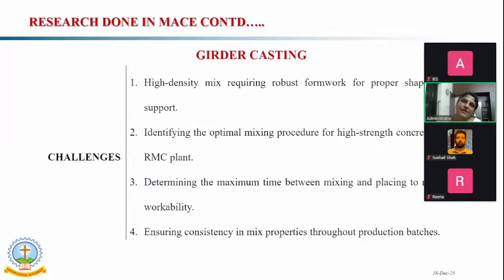The main challenge we faced in the girder casting was the high density mix. As you see in the flow of the fresh UHPC mix, the density was too high. The first time, that was unpredictable for us. When the flow came, the formwork was washed out. That was a very big failure the first time. The second time, we reworked the formwork design and added many bracings, so that we could support the high density fresh UHPC mix.